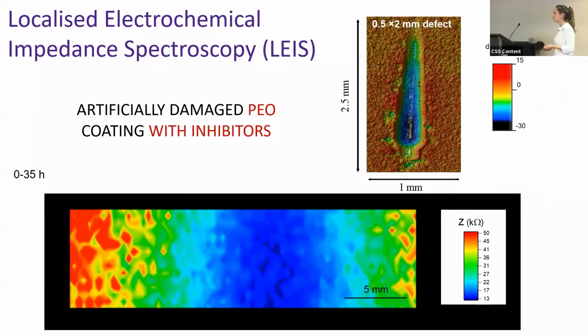So to evaluate the self-healing properties of my coatings, we use the technique localized impedance spectroscopy, which allows obtaining impedance maps at different locations. To assess the self-healing properties, we made an artificial scratch. Here we can see an optical profilometry image of my scratch. The red part corresponds to the coating, and the blue part corresponds to the exposed magnesium substrate.